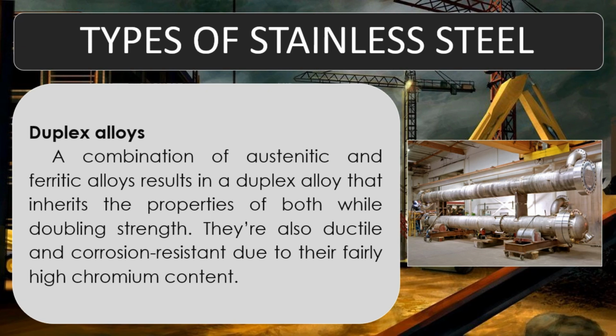The main differences in composition when compared with an austenitic stainless steel is that the duplex steels have a higher chromium content of 20 to 28%, higher molybdenum up to 5%, lower nickel up to 9%, and 0.05 to 0.50% nitrogen. Both the low nickel content and the high strength, which enables thinner sections to be used, give significant cost benefits. They are therefore used extensively in the offshore oil and gas industry for pipework systems, manifolds, risers, and in the petrochemical industry in the form of pipelines and pressure vessels.